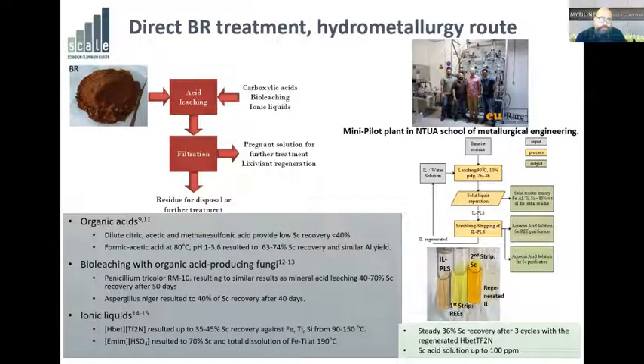Another idea was to use more exotic mediums for leaching, like carboxylic acid, bioleaching, and ionic liquids. Again, the same process, we're just not using mineral acids. With organic acids, we get very low scandium recovery, and there doesn't seem to be much, let's say, merit to this. But there is a case of formic acetic acid that resulted even in up to 74% scandium recovery and similar aluminum yield. Again, of course, these are separate papers. It's very hard to compare between them. There are some bioleaching studies out there. These are just some mentioned here, using different types of reagents to recover 40 to 50, even 70% of scandium.